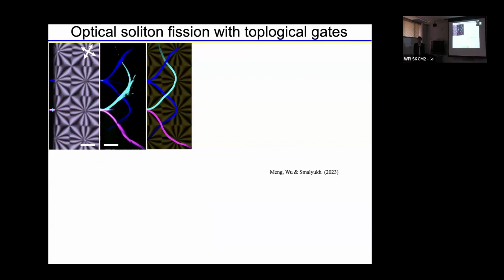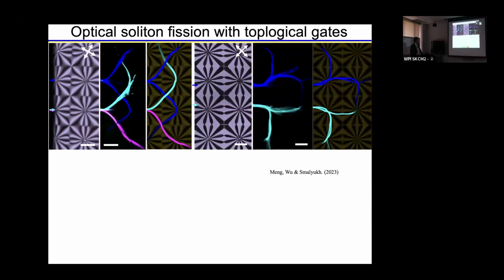Yet another very interesting thing is the fission of the optical solitons with the help of topological vortex lines. So you know that just like atoms can undergo fusion and fission, or nucleons, right? In a similar way, the analogs of atoms or nucleons, the solitons, in this case optical solitons, can do it too. And so, we can see that when we send the beam in some particular location that corresponds to these revolving gates, right? That, you remember, are the vortex lines of +3 that split into 6 half integers, we can generate daughter solitons. And again, we have very good agreement between experiments and modeling.